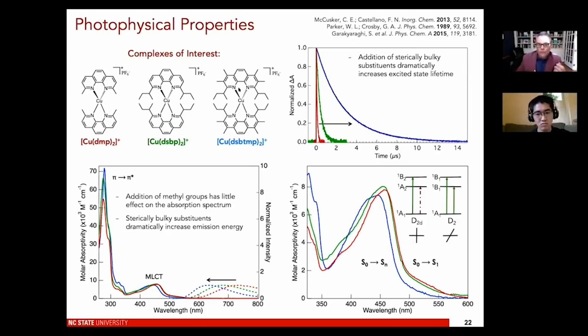And that ultimately manifests itself in the fact that you don't distort as much, and then the lifetime really gets very long because now your emission is a lot bluer, and then the radiative rate constant, the non-radiative rate constant decreases a lot because of the energy gap law. And that's really what is controlling everything.